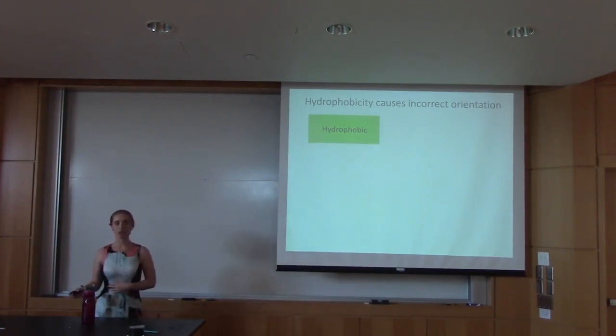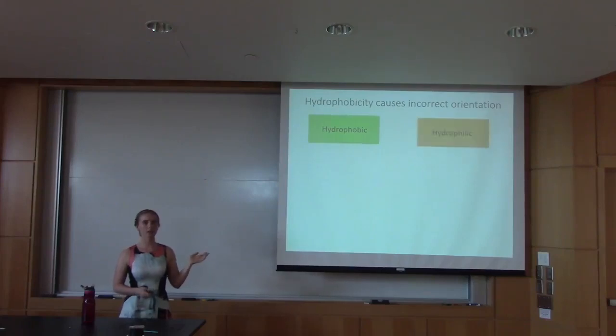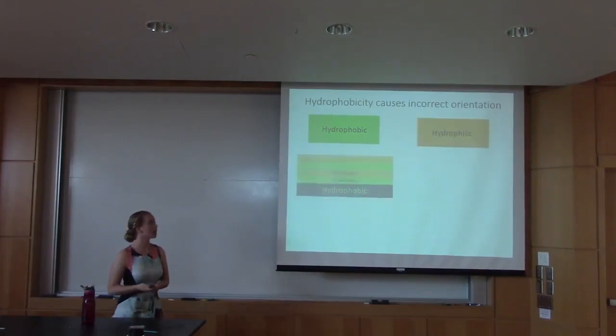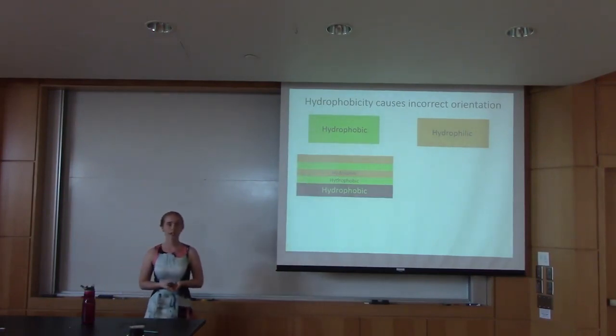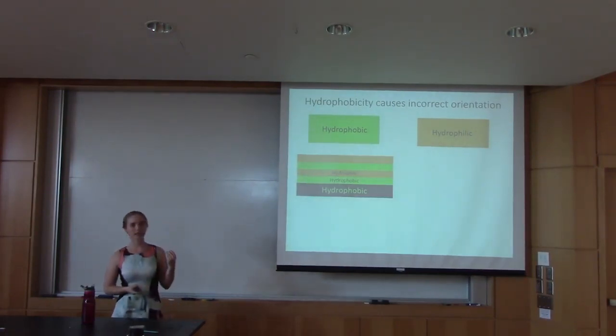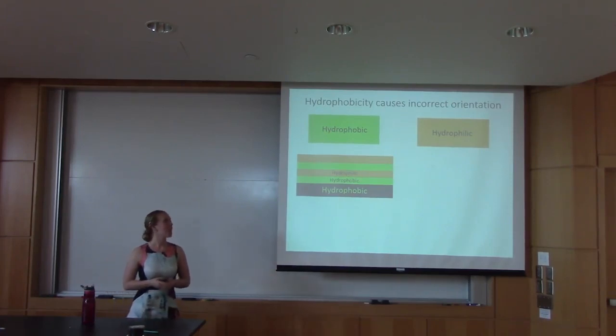And so to apply this to why our block copolymer has a different orientation, we go back to the individual units of the block copolymer. If we have a green part that's hydrophobic, whereas the orange part is more hydrophilic, then if we have a surface that is more hydrophobic, the green part is going to orient itself closest to this hydrophobic surface, and it's going to cause this parallel orientation.